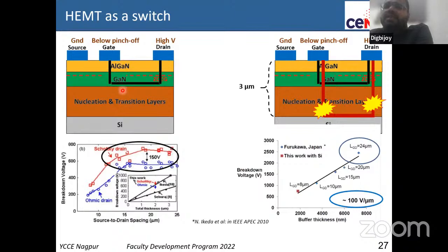So then you have to make these layers very thick. If you make these layers very thick, then you can minimize the chances of the field reaching silicon at the same voltage. So you have to not only make the device design carefully, but the material also has to be grown thicker to be able to block higher voltages. Now the problem is, the thicker you grow the material, more problems come on. There could be the possibility of cracking, for instance, because these layers are grown under stress. So there is always an interplay and always a trade-off between material growth, the devices and performance. It's not very easy. That's why it needs a lot of time, a lot of years of study actually.